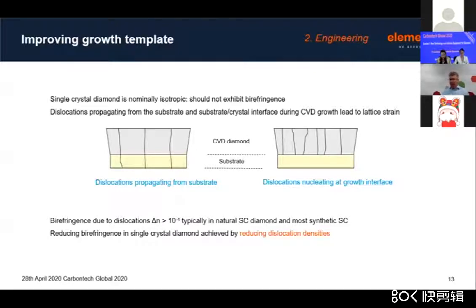As an illustration of that, I wanted to show you how, by improving the substrate, you can profoundly change the optical properties of diamond. Single crystal diamond should not be what's called birefringent. It should be isotropic and have uniform optical properties in all directions. So if you look through the diamond this way, you should see exactly the same as looking through this way. But it turns out that dislocations that propagate from the substrate into the diamond profoundly change the strain state of the diamond, which then gives the optical properties some aspect of anisotropy. And you can actually see these defects in the substrates. Equally, you can get them from the substrates, but you can also introduce them during the growth process.